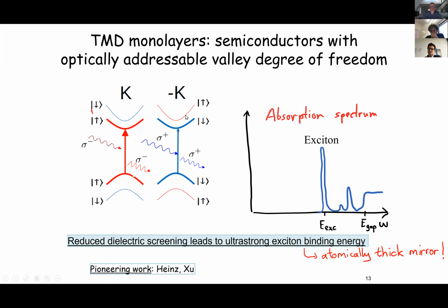Again, each valley has, of course, a spin degree of freedom, but because of the large spin-orbit coupling, one can, in principle, and depending on the choice of the material, focus on a single spin transition in each valley. And the time reversal symmetry, in the absence of a magnetic field, ensures that the two transitions are degenerate. And the selection rule for the optical polarization is set by the intracellular motion of the electrons in the two valleys. In one valley, they hop around in a clockwise direction, in the other valley counterclockwise direction, and that basically dictates whether they talk to sigma plus or sigma minus light.